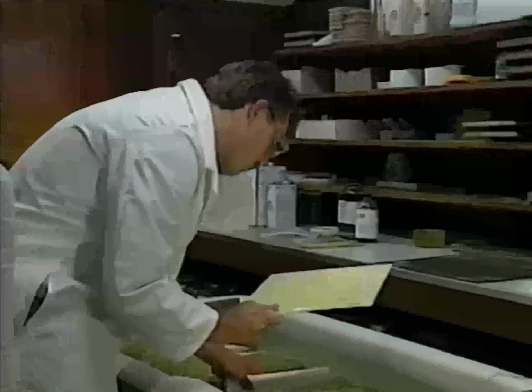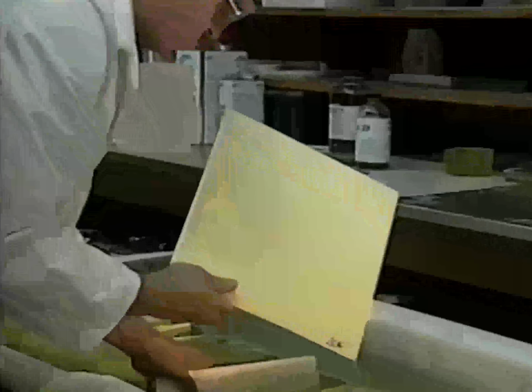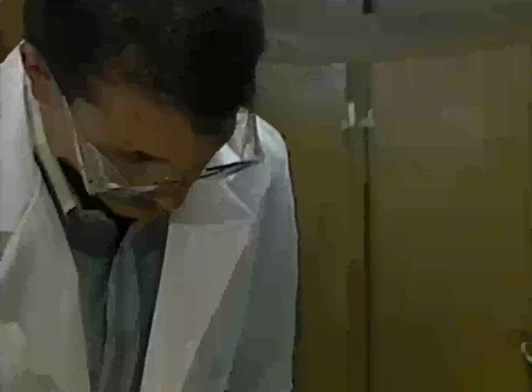We created a number of rigorous environments to produce blisters. One of the fundamental things determined from the testing is that blister development is directly related to moisture in the laminate. In this test, we subject coupons from existing fiberglass boats to an environment that accelerates blister development. With our ability to produce Gelcoat blisters consistently at an accelerated rate, we can better understand the cause of blisters and measure the effectiveness of repair techniques and materials.